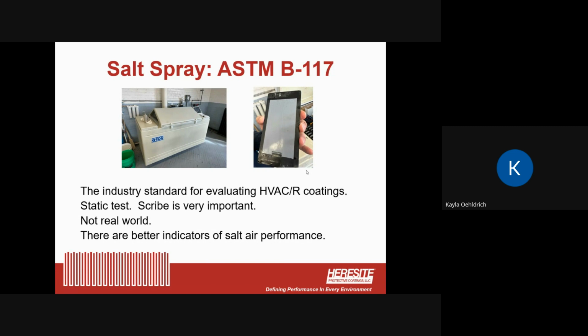So we have what are called coupons. You can see it at the right, which are aluminum panels that are sprayed with our different coatings. And then there's a scribe that's done down the middle, basically a scratch down to the bare metal. And it's put in the machine, and the amount of hours that it's in the machine relates to the amount of salt spray hours that it can withstand. It's very important to have the scribe on there, and there are many companies that don't put the scribe on there because if there's any defect in the paint film, you want to make sure that it's still going to perform and it's not going to peel.